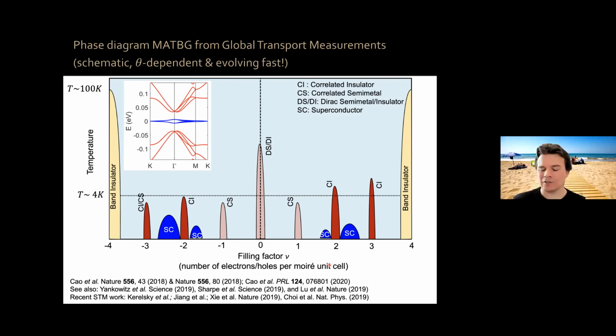How many electrons or holes are we doping per moiré unit cell in these flat bands? From charge neutrality, which is 0, you can add up to 4 electrons per moiré unit cell, then you reach the top of this conduction band. Because you reach the top of the conduction band, at 4 electrons per moiré unit cell, your chemical potential is here in a single particle band insulator, so you have a band insulator state, 0 conductance.